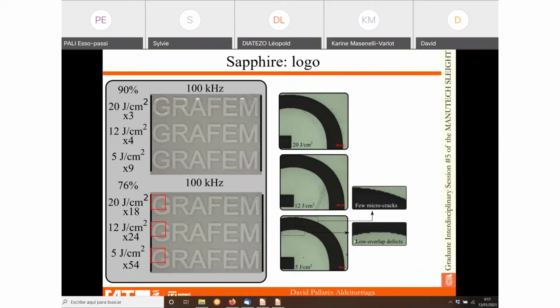We see a low resolution effect, like edges that are caused by the low overlap. As we are using a low overlap, the distance between inscription lines is higher, and then we have this pixel-like image. Okay, so here for sapphire, there is not a good candidate. We need to see what is best for a particular case. We need to perform a trade-off.